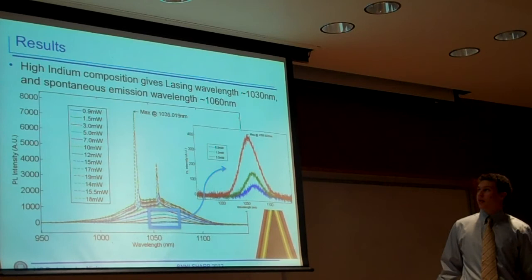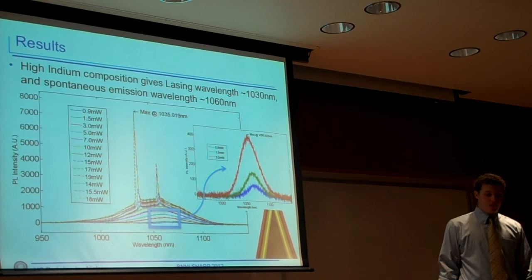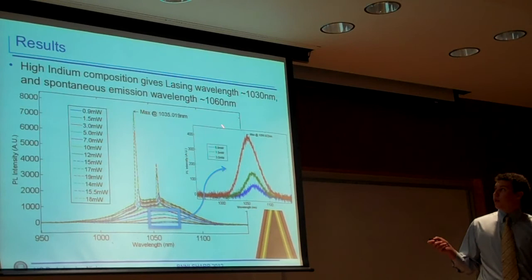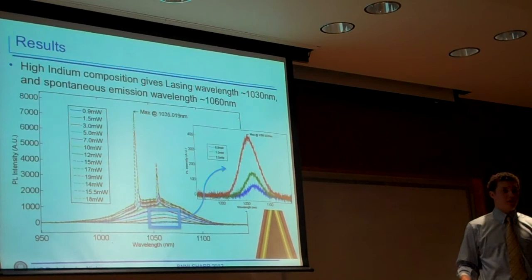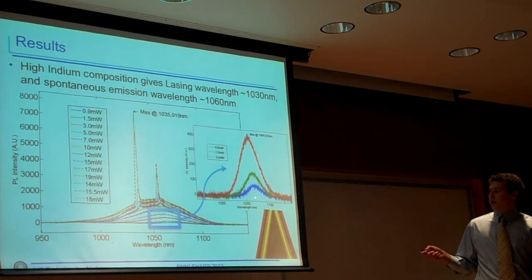Our results. From our high indium composition nanopillars, with the graded structure, we did retrieve wavelengths, lasing wavelengths, of higher wavelength than previously shown. Our lasing wavelength was around 1030 nanometers, whereas previously, in previous experiments, with the 20% was only 950. Our spontaneous emission wavelength was around 1060 nanometers, and the previous were around 970.